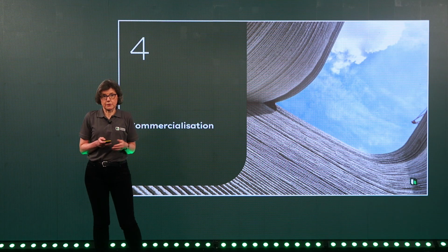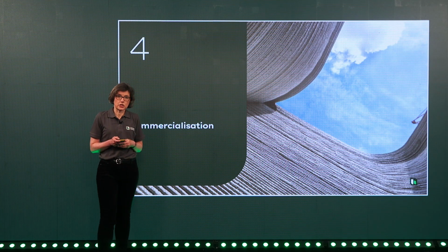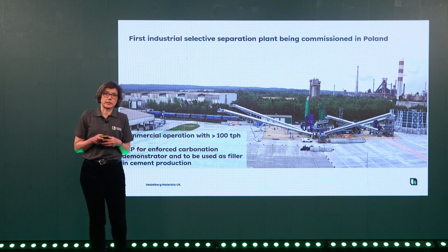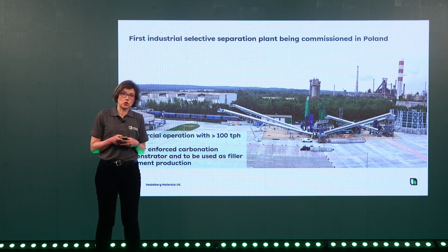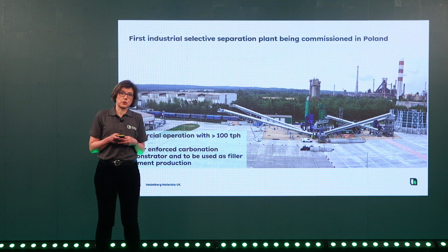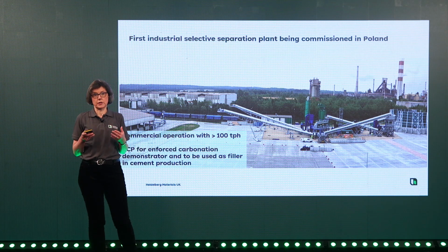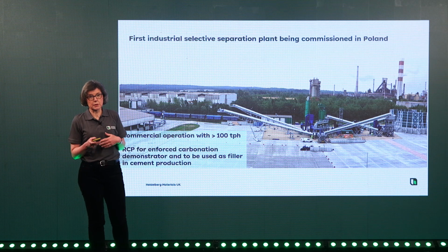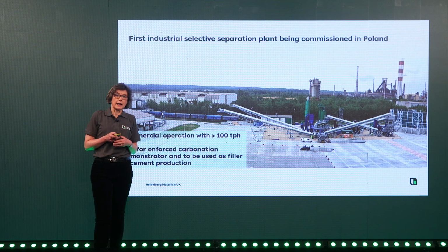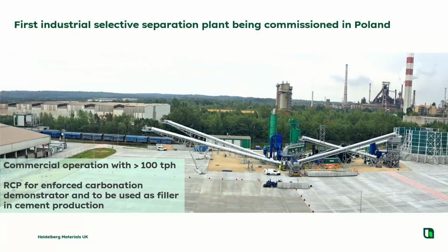What is the next step for us in terms of commercialization? What you see here is now the next industrial-sized plant, which is being commissioned currently in Poland, very close to our cement works there, and in an area where there is recycled concrete available as well. And we will be operating there with over 100 tons of crushed concrete per hour, and will then use the concrete paste from this process to use in the demonstrator to carbonate it.